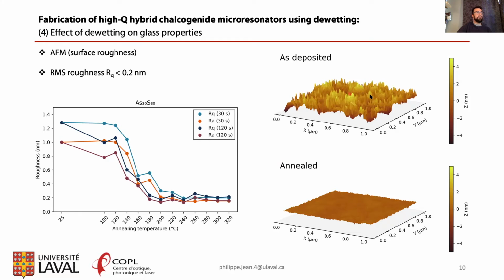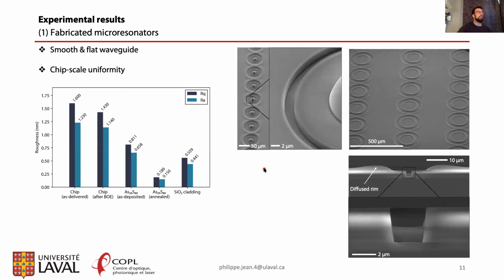And this can be seen here. This is basically the roughness heat map or 3D plot before and after annealing at 240 degrees Celsius. You can see that the roughness is very strongly reduced, and the RMS roughness is actually lower than 2 angstrom, which is an exceptional result for this kind of glass.